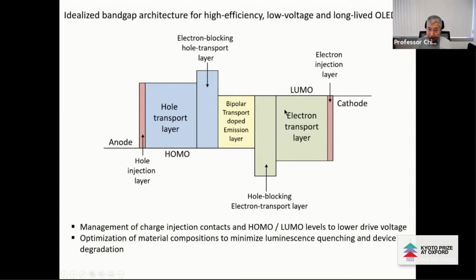So with this structure, you can optimize the drive voltage through the transport. You can use the particular layer to optimize the layer thickness for the optical couplings. And you can reduce the layer of this one here, or this 3-layer, to have a latitude to change the layer thickness to optimize the device performance, in other words.